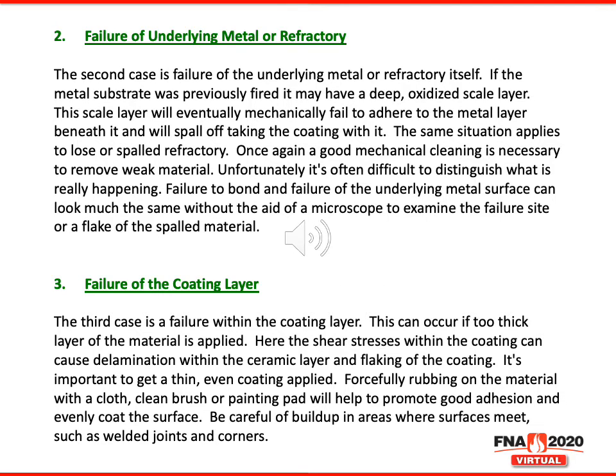The second type of coating failure is the failure of the underlying metal or refractory. In this second case, it is the failure of the underlying substrate. If the metal substrate was previously fired, it may have a deep oxidized scale layer. This scale layer will eventually mechanically fail to adhere to the metal layer beneath it and will spall off, taking the coating along with it. The same situation applies to loose or spalled refractory. Again, a good mechanical cleaning is necessary to remove weak material. In this situation, unfortunately, it is often difficult to distinguish what is really happening because failure to bond and failure of the underlying metal surface or refractory surface looks much the same without the aid of a microscope to examine the failure site or a flake of the spalled material.